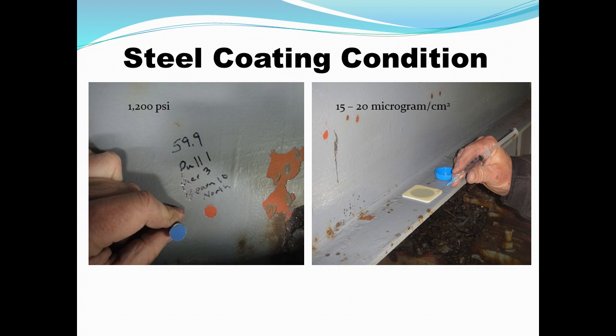This is a system. This bridge, the original paint is still on it. It was overcoated in 1997, 98. It had a spot clean with a spot application of aluminum-filled moisture cure urethane, a full coat of moisture cure urethane, and then a top coat with a 2-component urethane. And when we did the work in 2013, outside of this joint, I would challenge you to find a square foot of corrosion. This overcoat project was done for a little over $1 a square foot and was performing very well. But at this joint, we had a lot of problems.